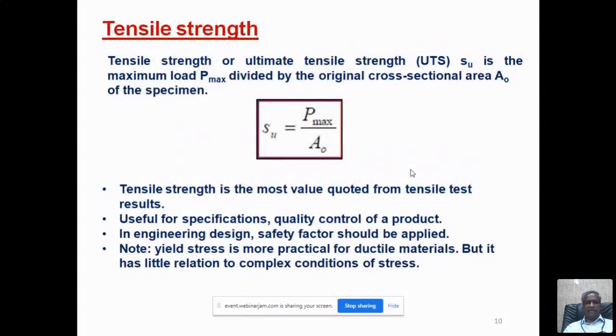And the tensile strength, as I explained earlier, is normally referred to as the ultimate tensile strength, UTS. UTS is the maximum load divided by the original cross-sectional area. The maximum load that the material can withstand, you can note down from the graph or during the test itself, divided by the initial original cross-sectional area. Initial means before testing you measure the diameter if it is a cylindrical specimen, or the thickness and width if it is a sheet or flat specimen. You can calculate pi by 4 d square for a cylindrical specimen, and width times thickness is the area for a sheet or plate specimen. Area is known, maximum load is known, divided by that gives the ultimate tensile strength.